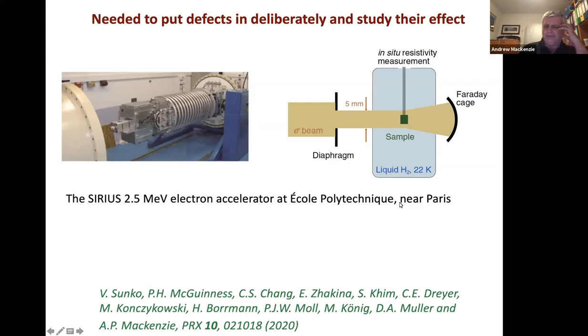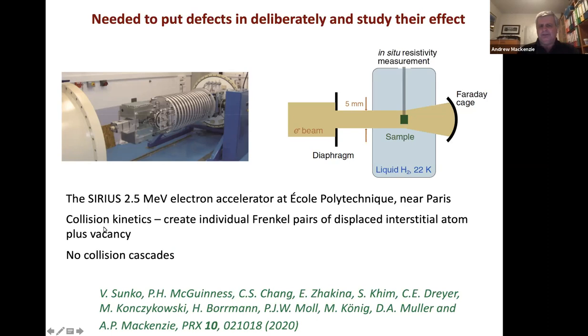The reason it's so special is that it gives you electron irradiation with electron beam energies of up to 2.5 mega electron volts. So that's about five or six times, or nearly 10 times, what you would get in even a high voltage TEM. And the reason that's so important is that these are very energetic, but very light particles. Rest mass is very small, so the collisions are quasi-elastic. The amount of energy that they're able to give to the atoms is just enough to displace them, but not enough to displace them with enough energy of their own that they bash into other ones and cause cascades of damage. So you're able to create individual what are called Frenkel pairs,